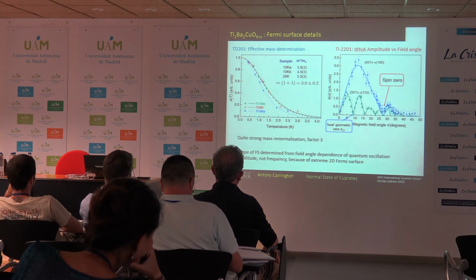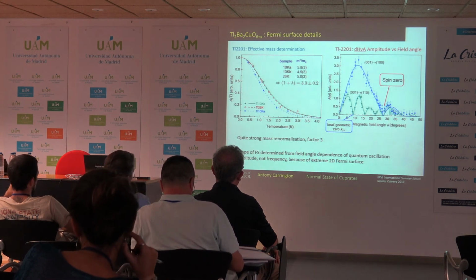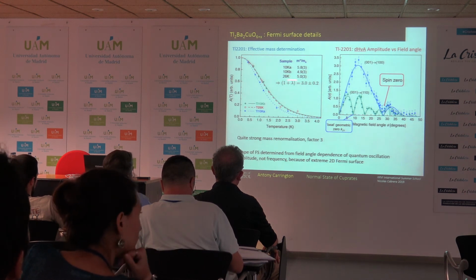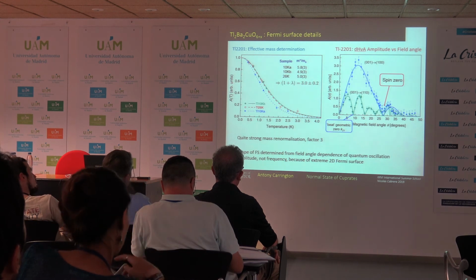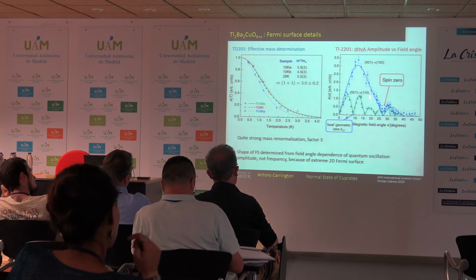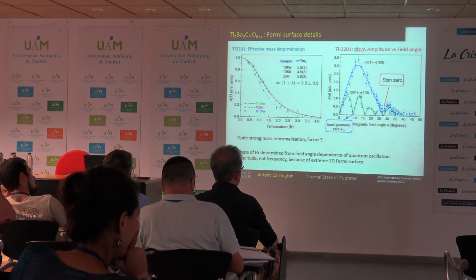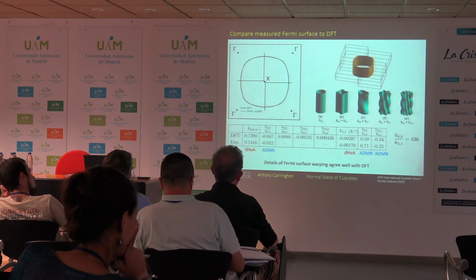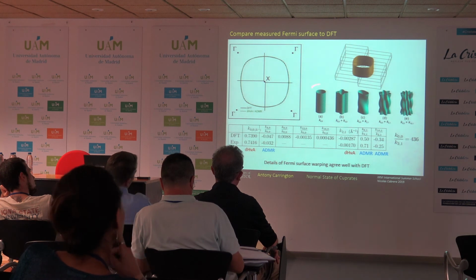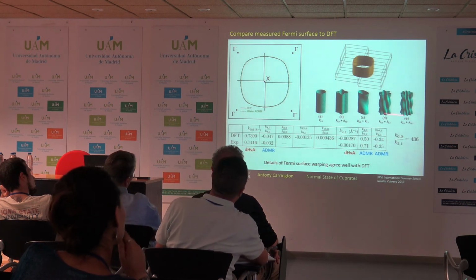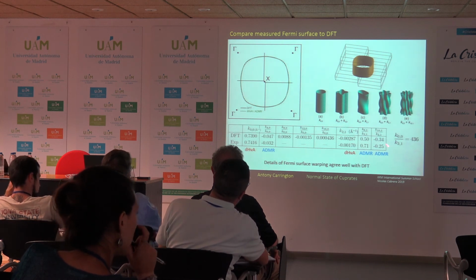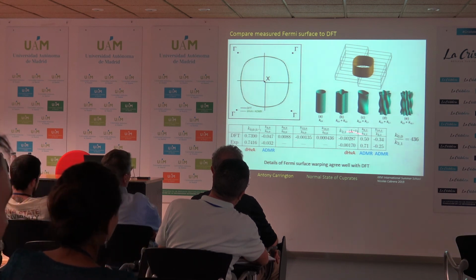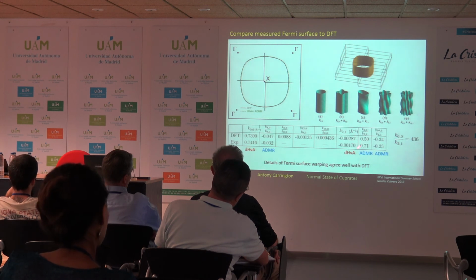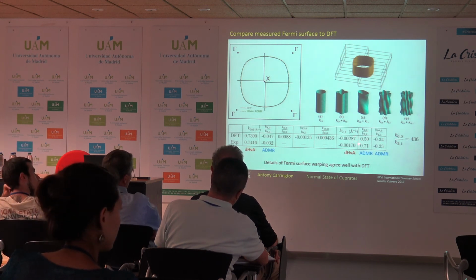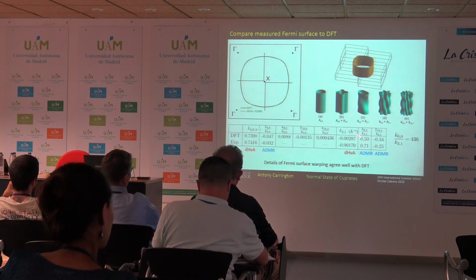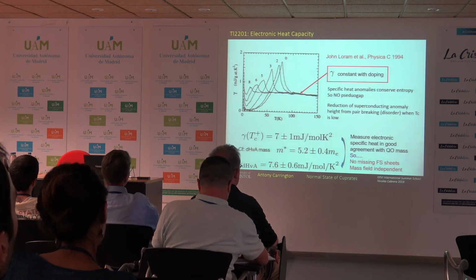Okay, so what do we know? Now we know in quantum oscillations, we can measure the effective mass. We know exactly what the doping is, it was 0.3. You can find the effective mass, you find the normalizations about a factor of 3. And then by looking at the amplitude and how the amplitude varies as a function of the field angle, you can work out exactly all of the little wiggles and wobbles in the Fermi surface. You can expand the shape in terms of these cylindrical harmonics. We can fit the DFT calculation, and then we can compare these numbers to what we actually measure. And they're in extremely good agreement, given how small these warpings are, you're looking at 1 part in 1,000 compared to the main warping, and I'd say that's pretty good agreement all in all.